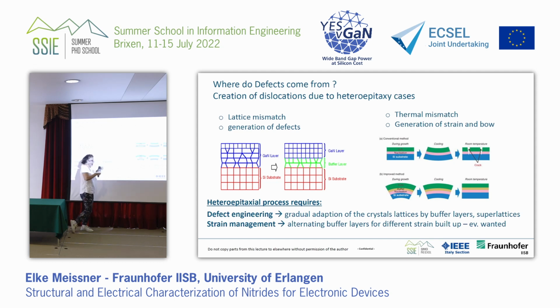This means that the energy is stored in the system, so it can be released by creating dislocations, bending. If you don't have plastic deformation in the form of dislocations, then you have elastic deformation, and your wafer starts bowing. This is, from the fundamental principle, what happens, what the dislocations are doing, and the disturbances are doing, and the strain is doing. So you need defect engineering and strain management in order to get what you want.